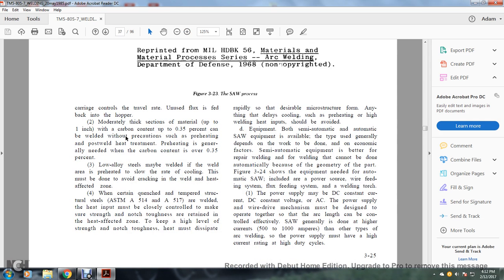Alright, moderately thick sections of material up to 1 inch, with a carbon content up to 0.35%, can be welded without precautions such as preheating and post-weld heat treatment. Preheating is generally needed for carbon content above 0.35%. Low alloy steels may be welded if the weld area is preheated with a slow rate of cooling. This must be done to avoid cracking in the weld heat affected zone.